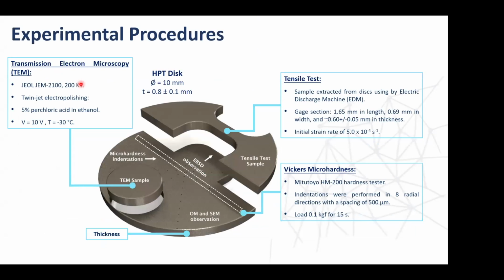So I'm going to go a little bit faster here. We investigated the microstructure by TEM too. We did EBSD observations and we did the tensile test. We have a capability to do this kind of micro tensile tests in Costa Rica as well. So it's a good way to see the mechanical properties.